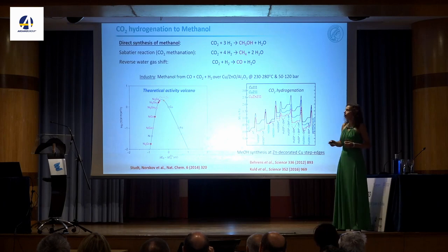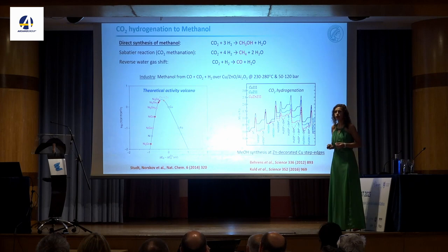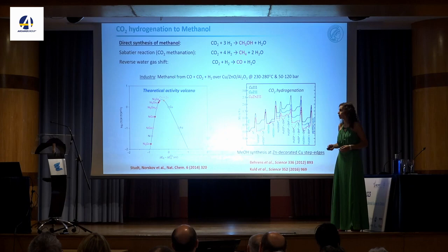At the same time, we wanted to figure out what is the structure and the composition of this catalyst under realistic reaction conditions. And realistic reaction conditions is not vacuum, and even we have some measurements also near ambient pressure. This is millibar. Realistic reaction conditions is when you go to 40 bar, to 20 bar. And this I will show you that we were able to do these experiments. Then we can figure out if there is a pressure gap.